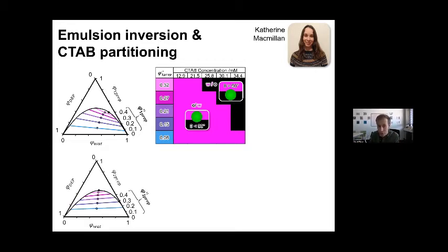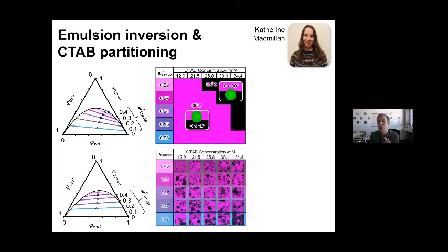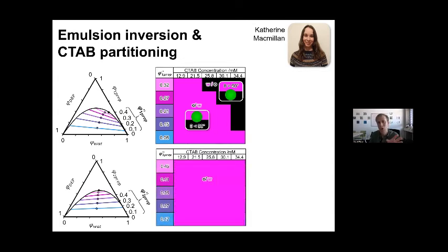With 2-propanol, on the other hand, you always get oil-in-water emulsions. That indicates the particles for 2-propanol are always too hydrophilic. They don't reach the suitable functionalization to stabilize the bijel.